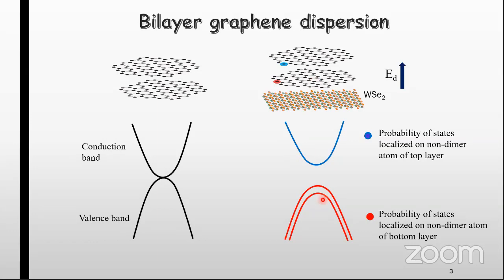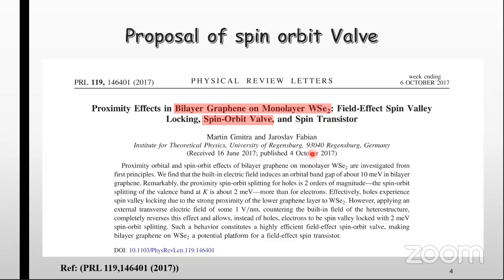So the valence band will be split. Now we can see the top layer is away from the WSe2, so there will be a weaker spin orbit coupling, and there will be a negligible splitting in the conduction band. Now there is a proposal of a spin orbit valve in this theoretical paper given by Gmitra and Fabian about this heterostructure, which I am going to discuss now.